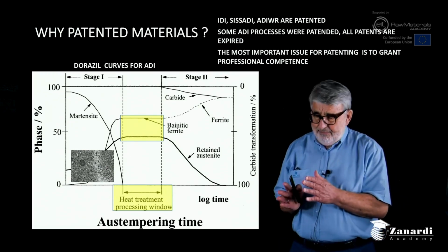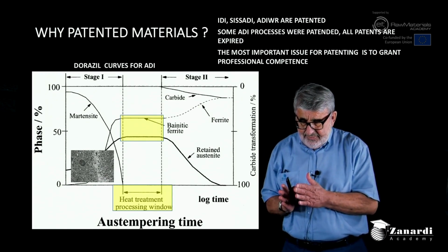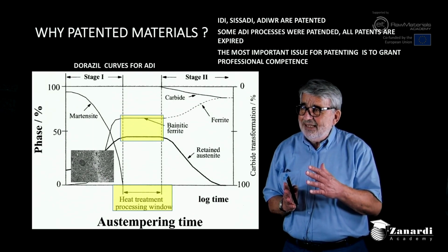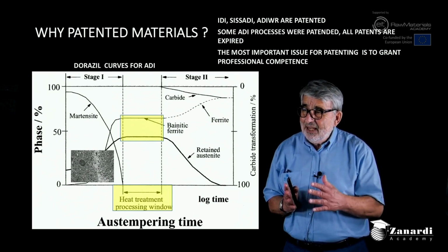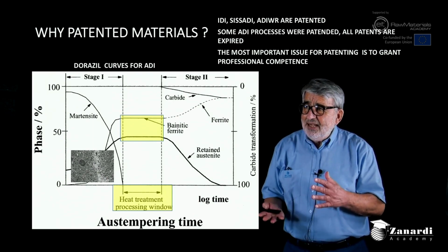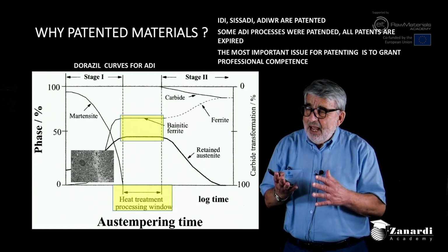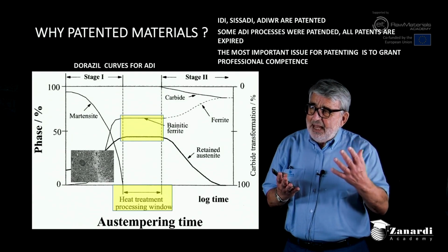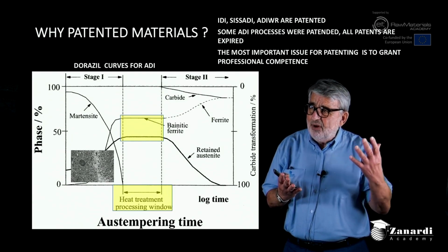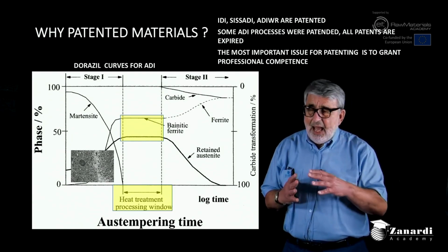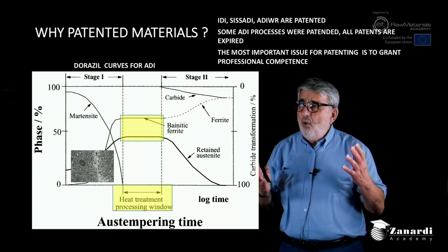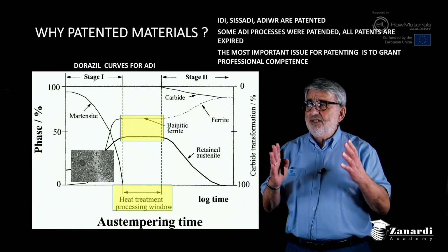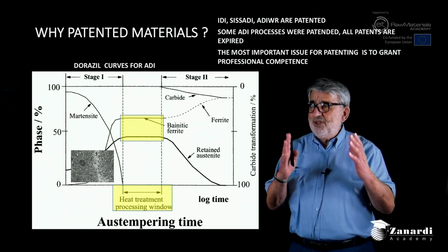During this process, the austenite content decreases, ferrite is increasing, and the residual austenite becomes more and more stable, until it reaches an equilibrium where the ausferritic reaction does not proceed anymore.